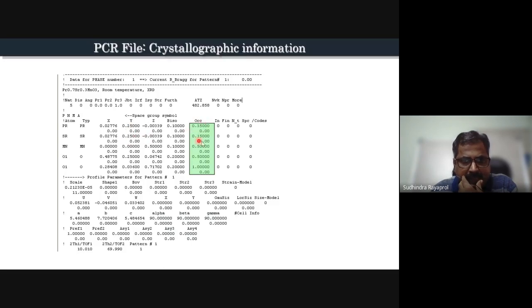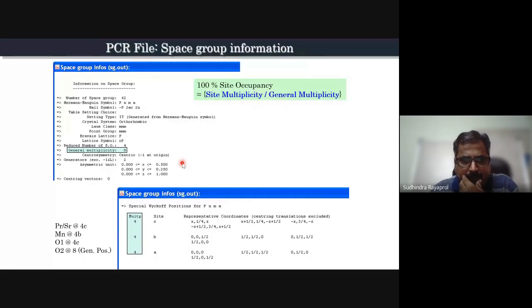Okay, so I have to just reduce their occupancies accordingly, but they'll have the same atomic positions. Then I have oxygen, then I have oxygen 2. Okay, 2 oxygen sites. So now if I go back to the PCR file information, they have general multiplicity of 8 and site multiplicity of 4. So according to my positions, I have praseodymium and strontium at site 4C, manganese is at 4B, and oxygen at 4-1, oxygen 1 at 4C, another one is at general position 8.